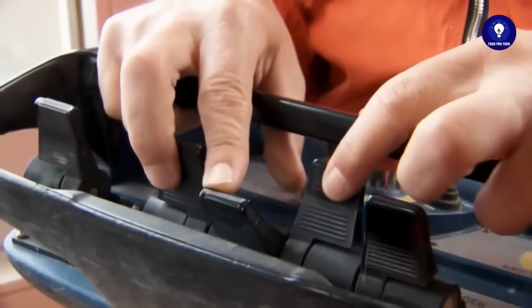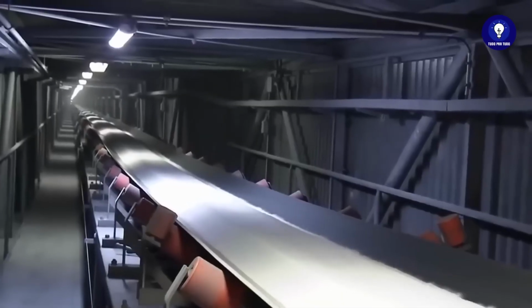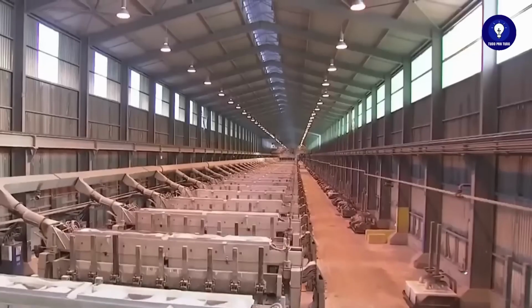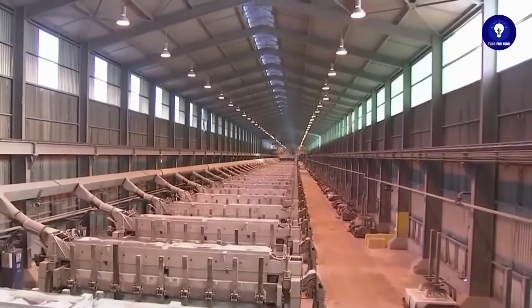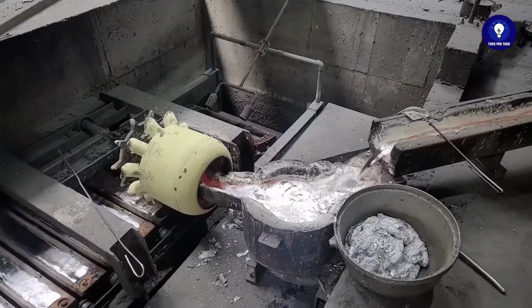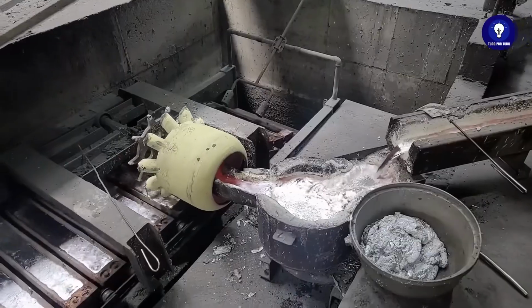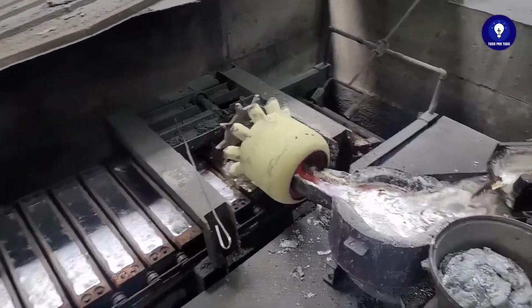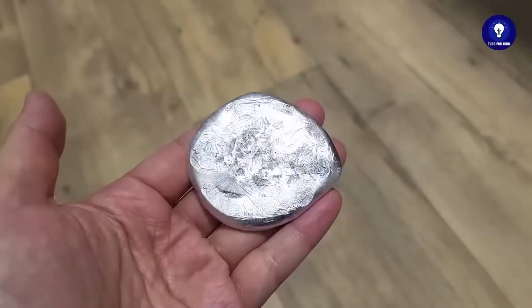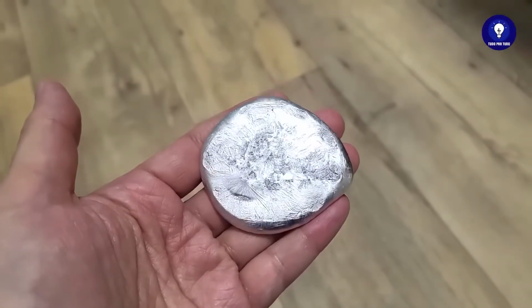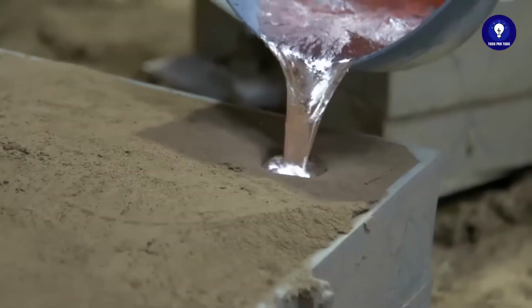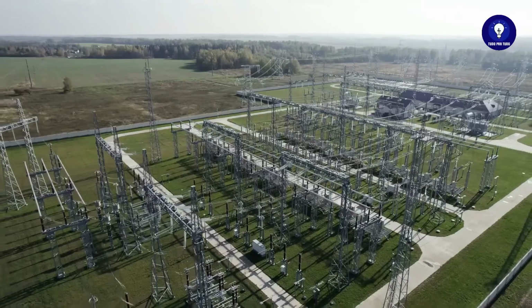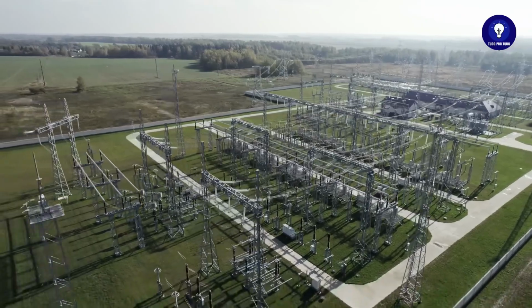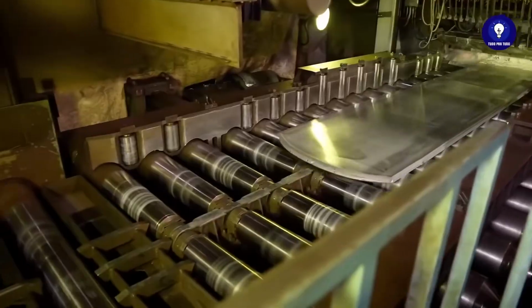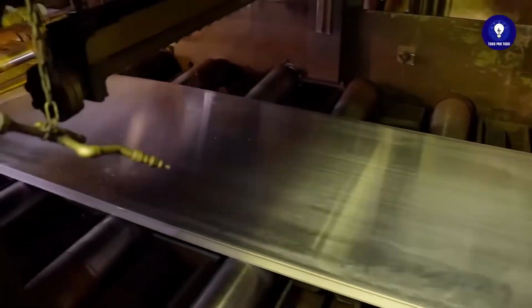The material is then placed on conveyor belts and taken to the factory, where the alumina is introduced into large electrolytic tanks filled with molten cryolite. The cryolite lowers the melting point of alumina from about 2050 degrees Celsius to about 950 degrees Celsius. To obtain pure aluminum, it is necessary to separate the oxygen atoms, which keep it strongly bonded, a process that requires a huge amount of electricity. That's why aluminum is known as electricity in solid form.